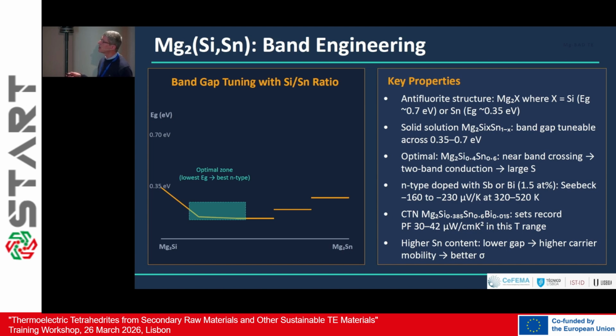Okay, now going deeper into magnesium silicide, we can tune the band gap by playing with the ratio between silicon and tin. So it is possible to tune the band gap between 0.35 and 0.7, which is quite large. So it's quite good. It's possible to have large Seebeck coefficients, and actually in our case we got a record, higher than 42 microwatts in this temperature range, so at low temperature. So it's really possible to get proper power factors.